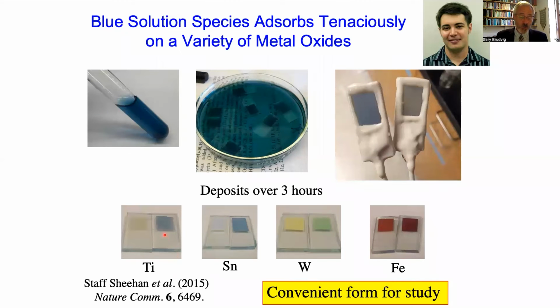It's very strongly adsorbed. So in the case of titanium oxide, we found that the only conditions which will remove the catalyst from the surface are conditions that dissolve titanium oxide. So it's very tightly bound. We believe it's grafted onto the surface through very strong titanium-oxygen-iridium bonds.